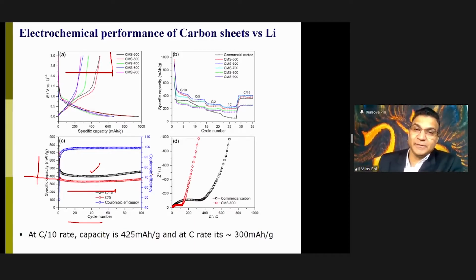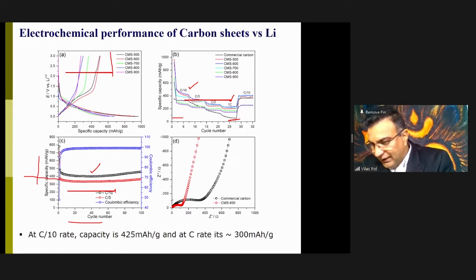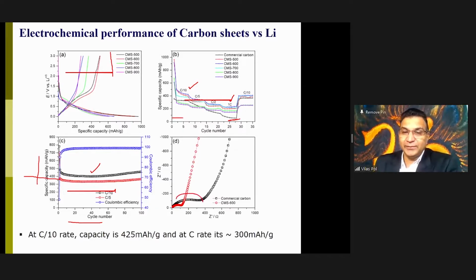That means this material is not only behaving like a standard graphite, but even better than that because of its unique architecture. This plot explains the rate studies. Namely, if you even use 1 hour to charge and 1 hour to discharge the battery, you still get very nice capacity. On the contrary, the standard commercial carbon gives you very small charging at fast charging rate. But this is behaving well because of that thin sheet which can charge and discharge very rapidly. This is impedance spectroscopy that is important to know that this does not have too much resistance in the system. So commercial carbon has this bigger semicircle versus this packing peanut derived carbon has a small one. So there are plenty of advantages.